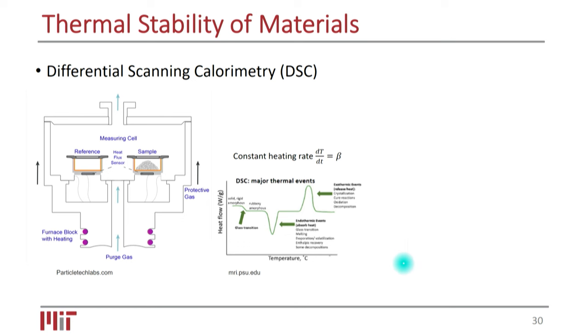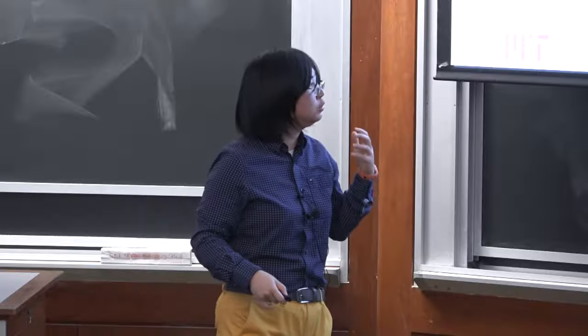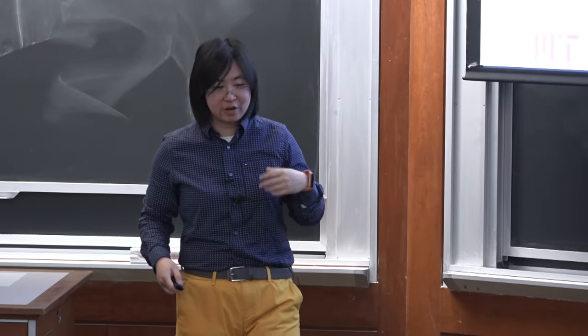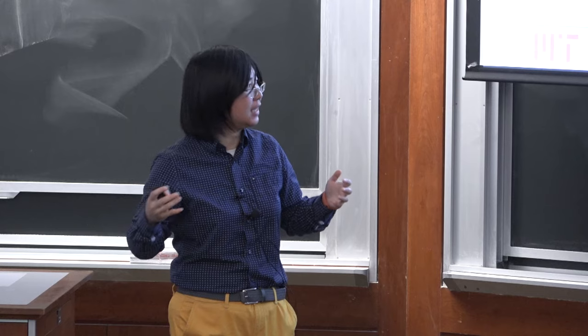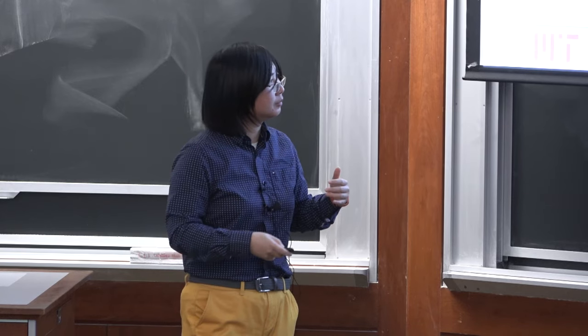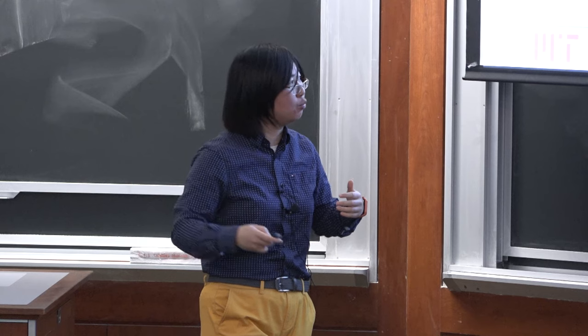On this x-axis, as the heating goes up, the system temperature increases, and we can track the heat flow comparing the sample and the reference. And whatever peaks with the bottom shape would be endothermic, meaning that it's absorbing heat. And for a tip-up shape, we have an exothermic reaction, meaning that we are releasing heat. So thermal runaway would be associated with those exothermic reactions, that generate heat and further trigger other reactions that would generate more heat.